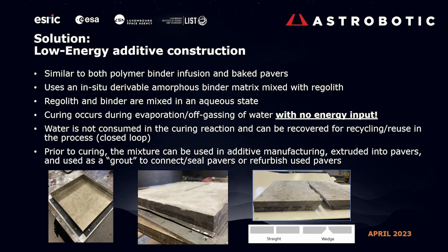Because it's also a paste, we're able to make these pavers, and then we're able to grout between them as well to make larger and larger structures out of the same material. You can see some of the pavers that we use to test out the landing pad technology. We start with this square, that's probably 25, 30 centimeters in size. We've made the pavers, and then we cut some of them in half, and then grouted them back together with the same material.